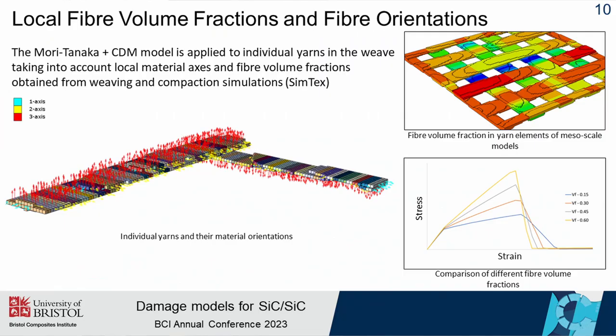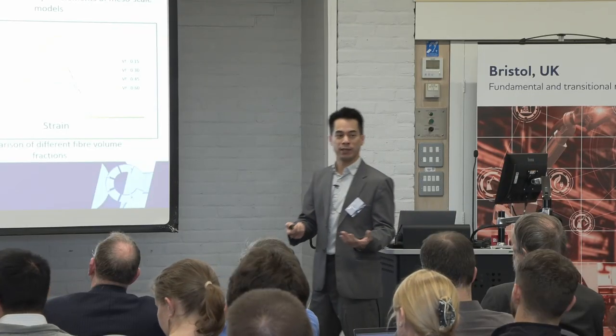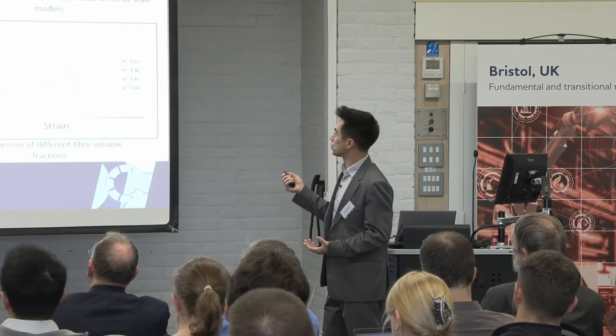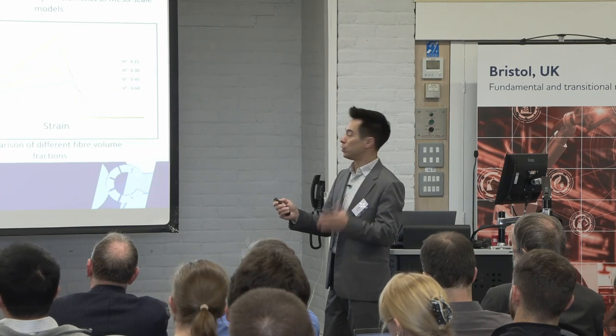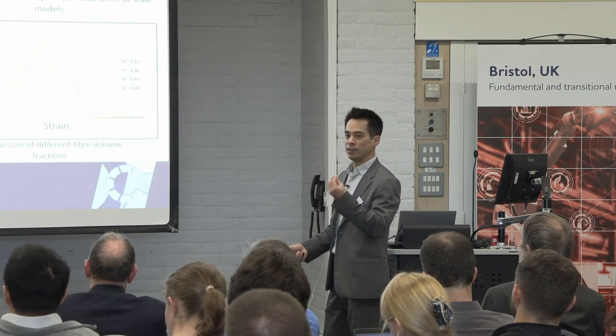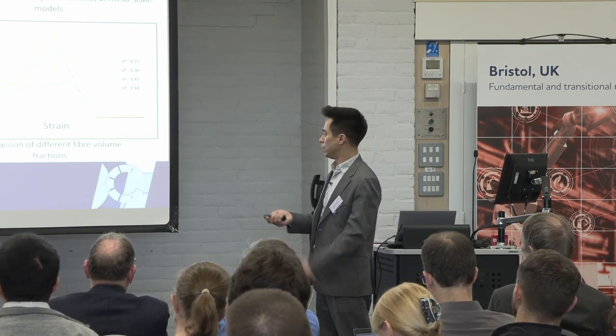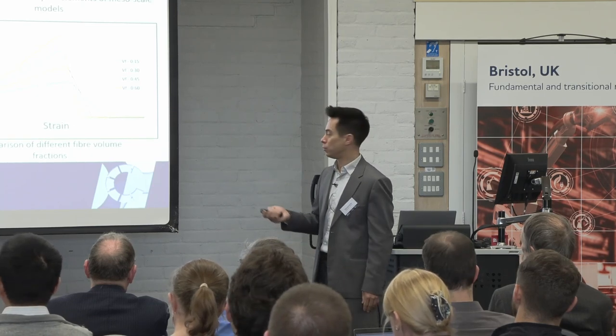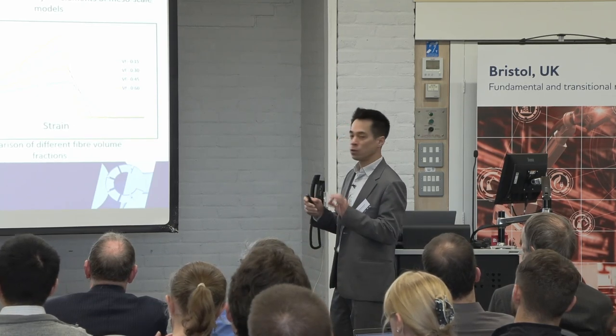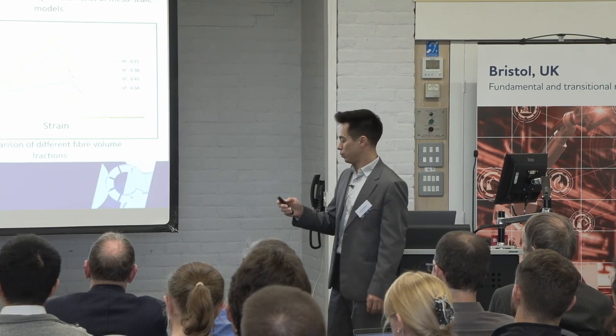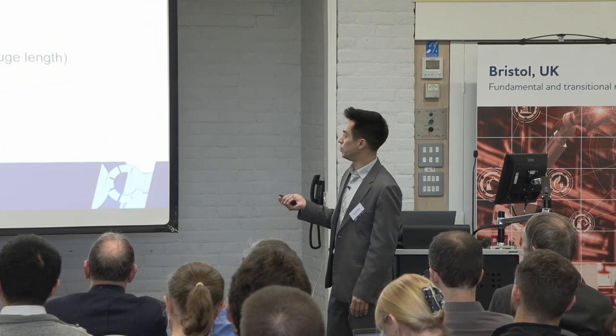So from those draping and compaction simulations, we not only get the local orientation of the yarn, but also the local fiber volume fraction. And the fiber volume fraction, as we would expect, has an effect on the stress strain behavior of that yarn. Okay? So these models, although they are voxelized models, they have this extra layer of faithfulness or fidelity, which is the local variations in material orientation and fiber volume fraction.